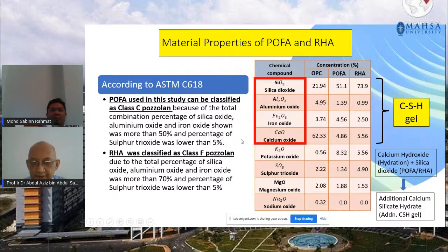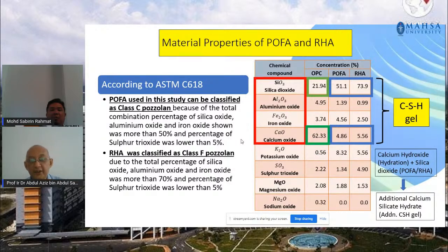And as you can see from this chemical composition, both POFA and rice-husk ash have a very large amount of silica dioxide, 51% and 74%, respectively. But unfortunately, for the calcium oxide, both POFA and rice-husk ash have very little as compared to the ordinary Portland cement. As you can see there, about 22% of silica dioxide, much less than POFA and RHA, but a whopping amount of 62% of calcium oxide as compared to POFA and RHA.